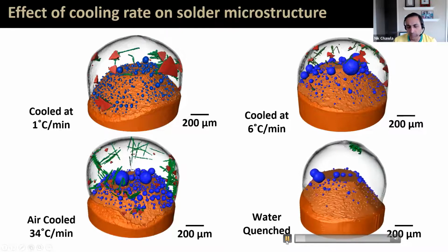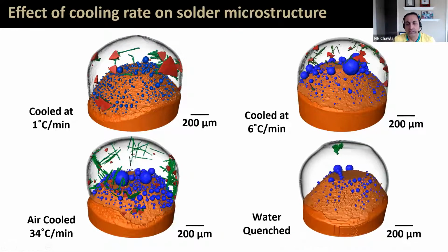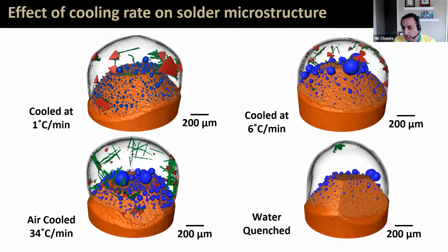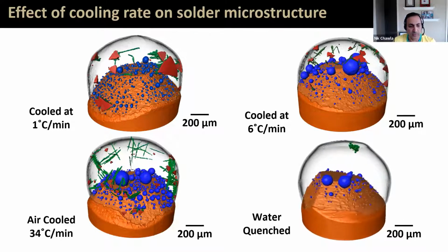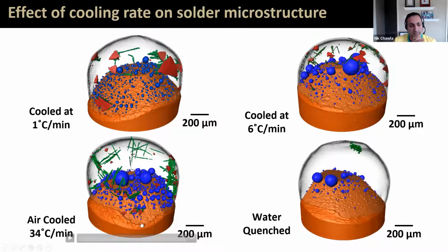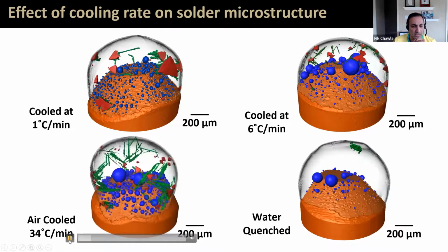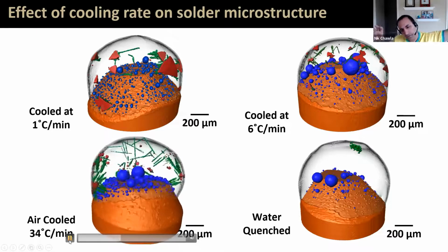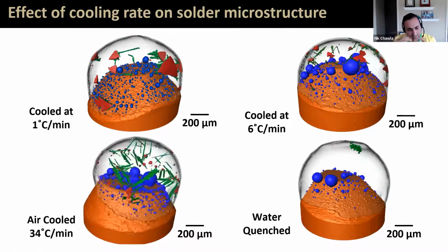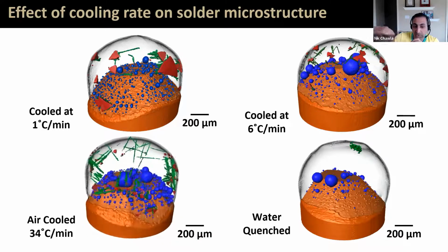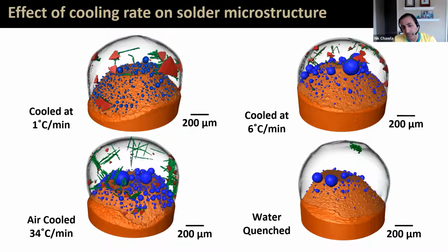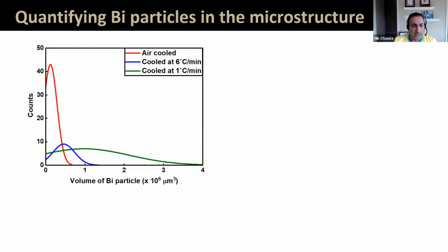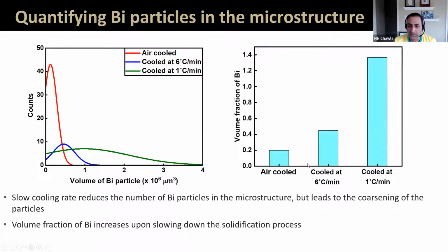If you have a water quenched sample, the bismuth gets trapped in solid solution and it doesn't come out, so you don't see any bismuth particles formed. That's the other extreme. But in between, somewhere between very slow cooling and very fast cooling, you still get some bismuth particles, but they're finer and smaller in nature, and you get more of these tin dendrite needles. So we've quantified the volume of these bismuth particles. You can see here a volume fraction.